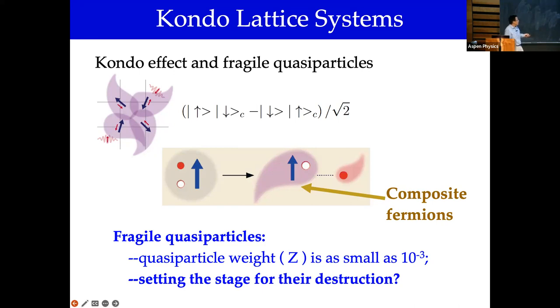So if you have these three objects forming a bound state, you can kick an electron out, that's a bare electron living on the fast lane, or you can have this composite object, which has spin one half and charge E or minus E, and so that object has the quantum numbers of a bare electron. And that's in fact a picture of this particular kind of quasi-particles which I've introduced generally, except that this is a very cumbersome object to move around. So if you ask what's the Z, the weight of the bare electron that's living in this quasi-particle, Z turns out to be very small. It's three orders of magnitude smaller than one. It's about 10 to the minus three.